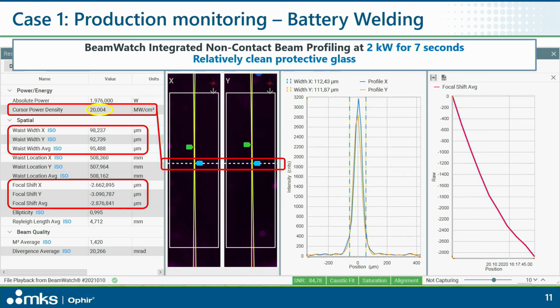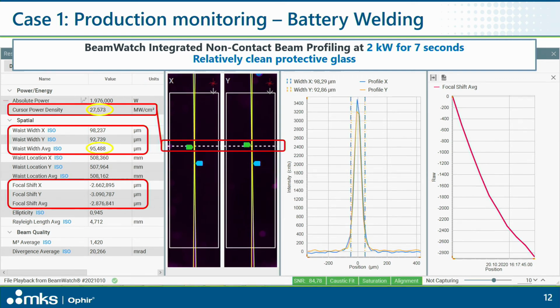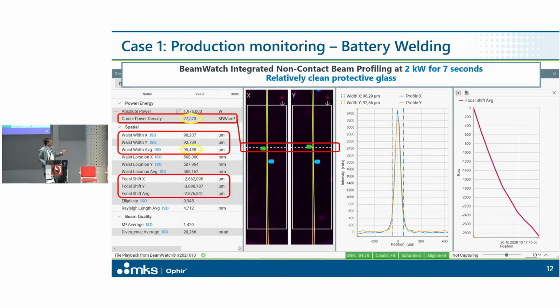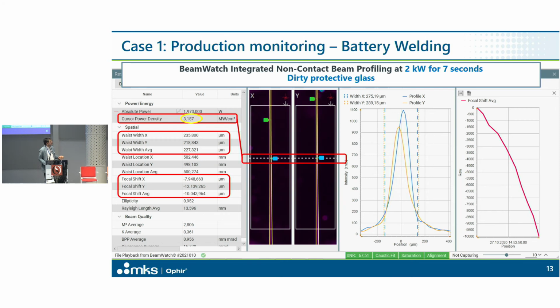Well, what happens? That is 2 kilowatt with a relatively clean protective glass. We use this word just because it's not possible to say it's absolutely clean or not clean, but you have this information. What happens? The measurements give you that the real waist is just up here, still about 100 micron, so not so far away, but you see that your power density is increased. We go up to 27 megawatts per square centimeter. Could be good, could be not. Let's see what happens in the welding process, but what happens when we change this condition, when we have a dirty protective glass?